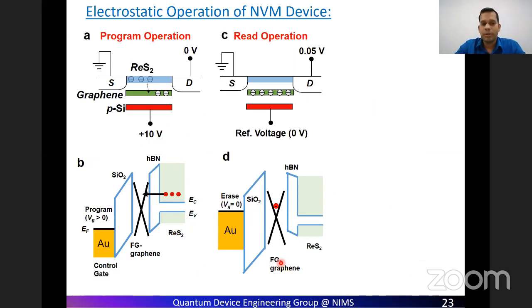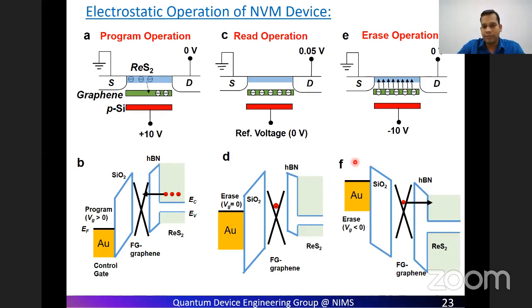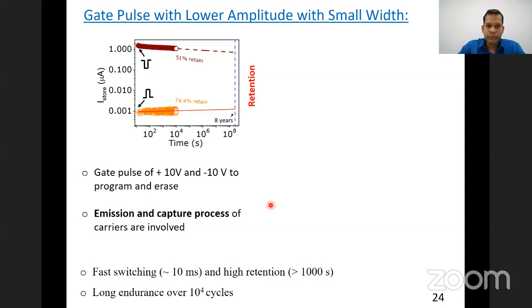So the basic operation I have shown here. To program the device, we need a plus 10 volt gate bias. That deforms the band alignment across the vertical direction, and the conduction electrons from this rhenium disulfide can tunnel through hBN and be stored in the graphene. To read this information, we need to release the gate bias and apply a small drain bias, so that we can read the charge stored information. And to erase that, we again need to apply a negative gate voltage, and then the band deformation takes place in the opposite way, so that the stored charge carriers can tunnel back to the ReS2 channel. So this is the operation technique we use, and the retention and endurance we have studied further.